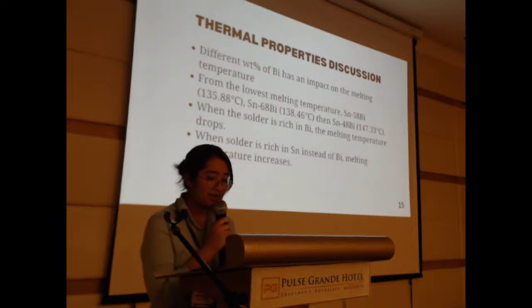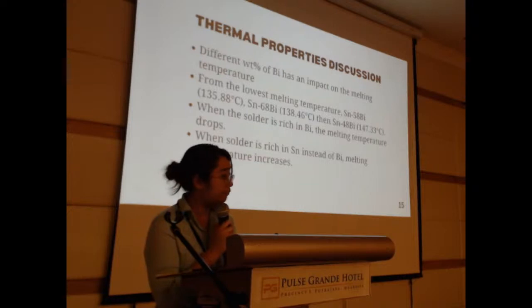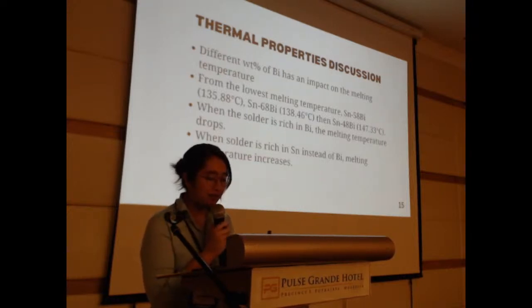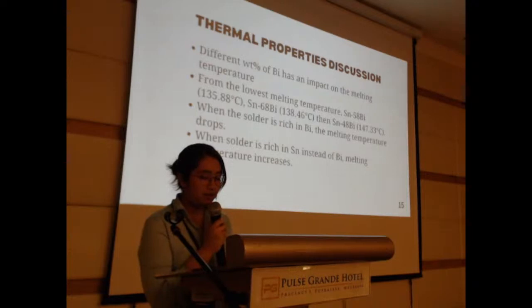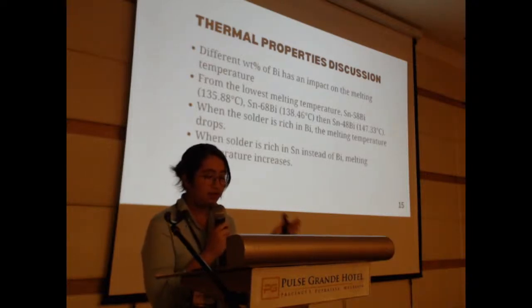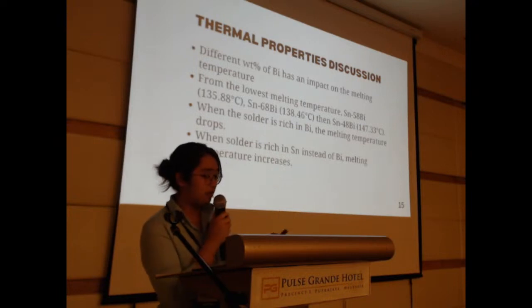So from the results, we can see that bismuth definitely has an impact on the melting temperature. Okay, from the lowest is 58% of bismuth, followed by 68% and also 48%. So it's deduced that rich in bismuth, the melting temperature drops, and if less bismuth, melting temperature increases.